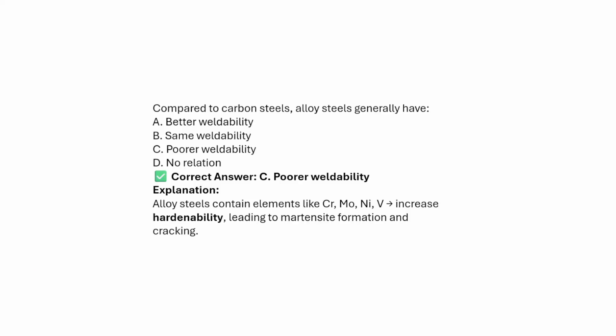Compared to the carbon steels, alloy steels generally have: better weldability, similar weldability, poor weldability, no relations. The option will be C, it is poor weldability. Generally, low carbon steels have good weldability. Alloy steels contain chromium, molybdenum, nickel, and vanadium. Those increase the hardenability, so lead to martensitic formation and cracking.